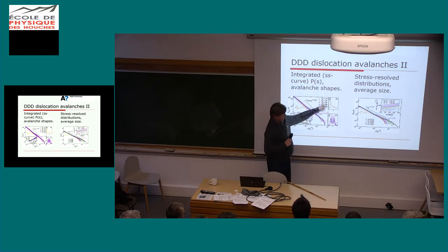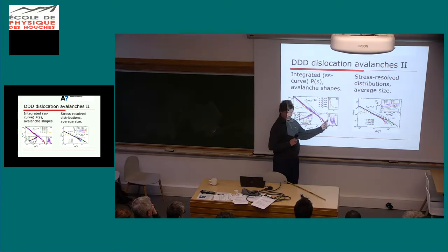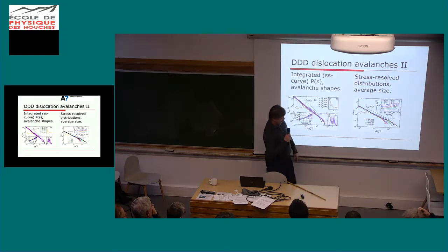These subplots show you how complicated this issue is, because you can look at single dislocations, or segments, as they behave in these three-dimensional systems. This is an example of the signal of a single avalanche. It has a peak and decays slowly, but then you also have collective avalanches if you go to larger avalanches. So there's a mixture here of single-particle behavior, meaning a single dislocation exploring a random force landscape. Then if you start to involve more and more dislocations, this starts to look like what you would expect, maybe not a real parabola for this avalanche, but something like that.